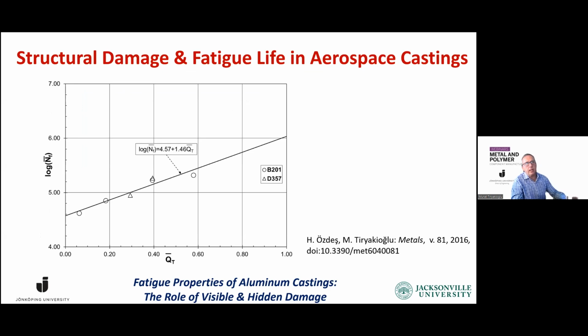So I asked a master's student to look into the aerospace literature, and we did the same thing. These are coupons excised from real aerospace castings tested in fatigue. These are a little bit different geometry, flat specimens, but the link is clearly there. The link between fatigue life, log of fatigue life, and the quality index or damage.